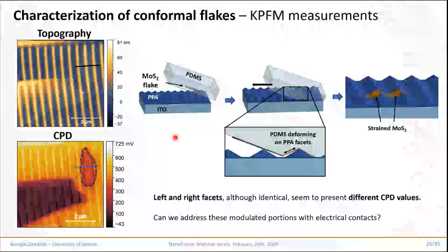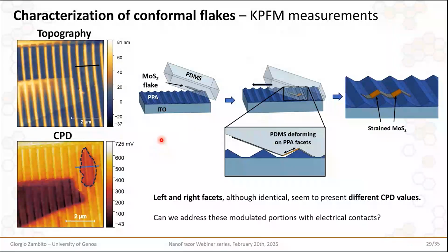The explanation that we devised for this effect is that when you transfer the flake through the PDMS, you are giving directionality to the transfer. This should not have any effect on a flat surface, but in this case we are exploiting a three-dimensional faceted grayscale defined surface. Since our flake is coming from one direction, on one side it will not present any kind of stretching effect, but on the other side, the PDMS will be deforming along the facets, and hence the flake will also be deforming and stretching. After the transfer, it will be left with a localized strain on certain facets. So this is an already interesting result, which we were able to observe by Kelvin probe force microscopy.